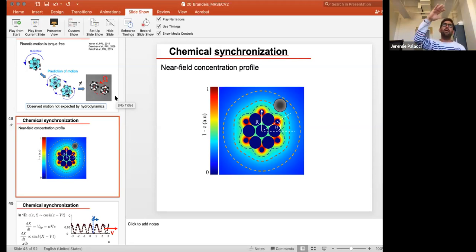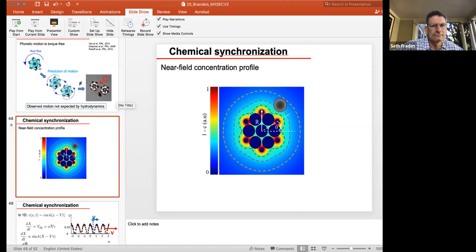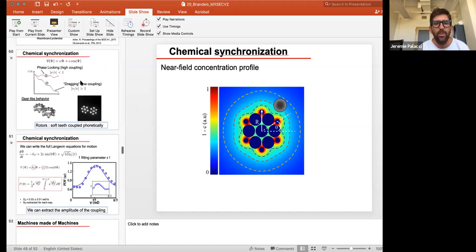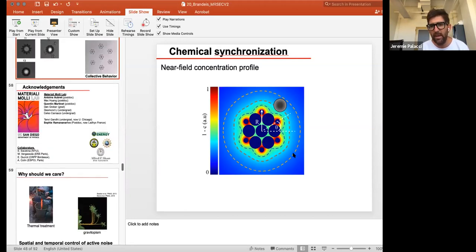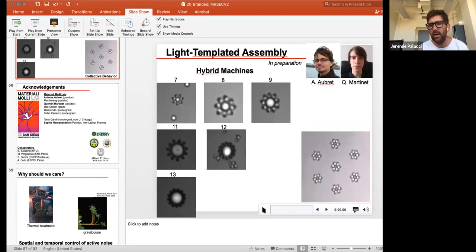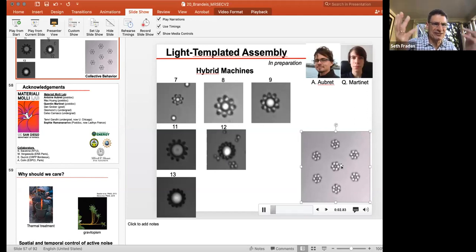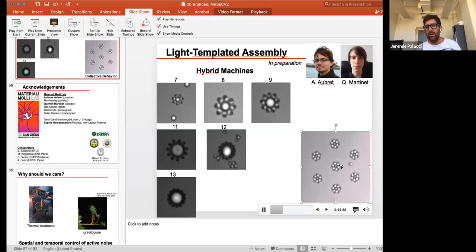My recollection is we got more like a decay like 1 over r to the 3 or 4 for the correlation, and we don't know why. About that question, the last figure of the paper is just discussing it. We didn't look for pairs of swimmers. What we did was more or less this experiment, which was even more painful at that time because we didn't have control of the chirality. We made a bunch and sorted them so we would have 7 co-rotating, and we could vary the relative distance from the center. We see that the crown is co-rotating, and we measure the co-rotation speed of the crown as a function of the distance to the center, and we have a decay which is way, way less than what we predict. Well, that's good, because otherwise you would never observe it. So the synchronization, we still observe it, and it's decaying 1 over r to the 8.